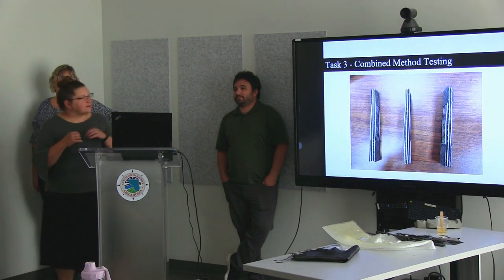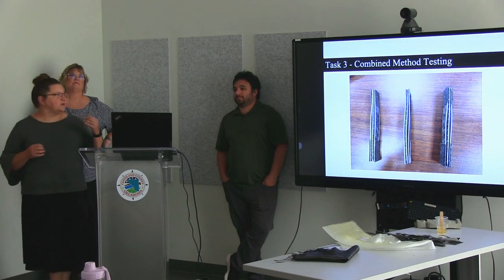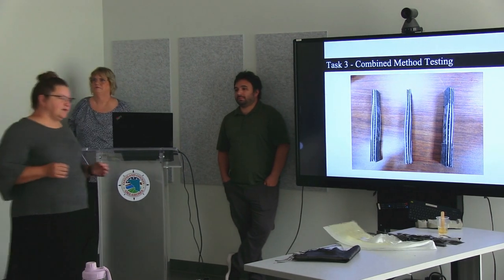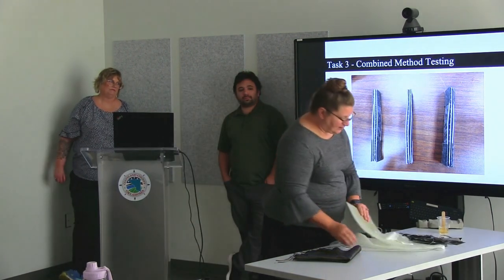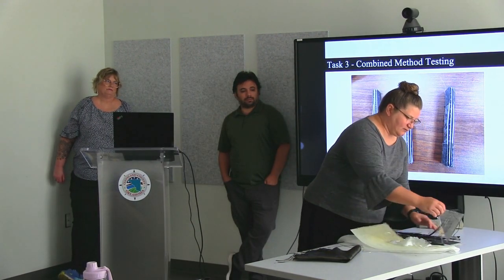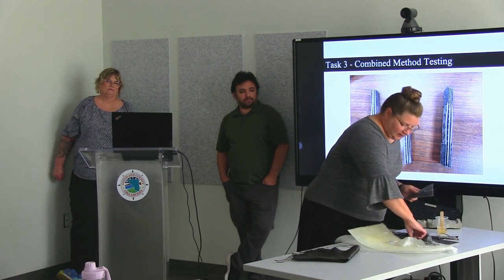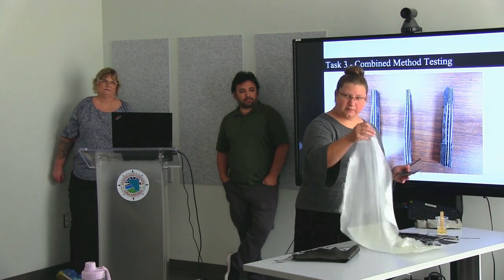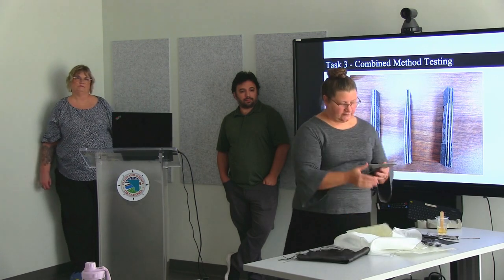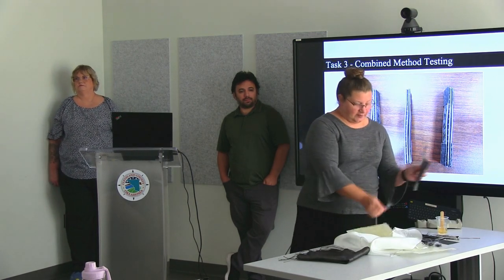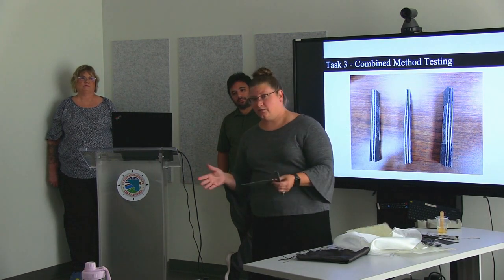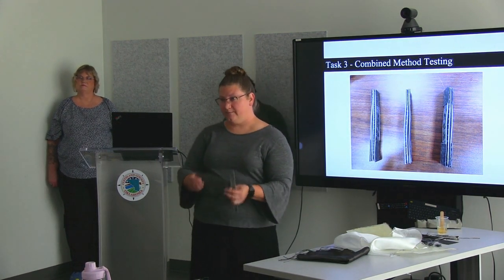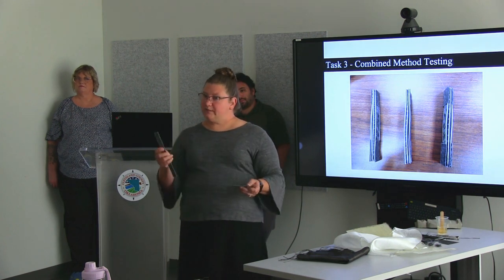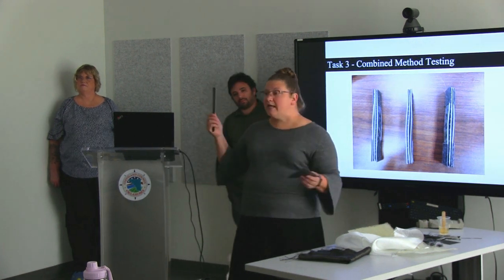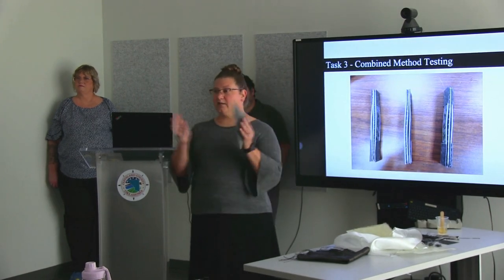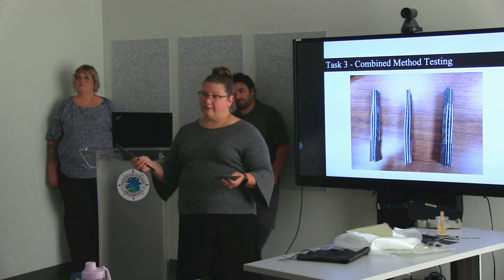So that brings us to our third method of testing. We decided to do a combined testing. So we did a wet layup where we used one layer of the glass fiber, a layer of carbon, and another layer of the glass fiber. And from there, we picked the easiest angles to cut manually. So we did one piece for each sample at the 0 degree and 2 pieces, one for each end, because it's got to be symmetrical all the way through, at the 45 degree angle.